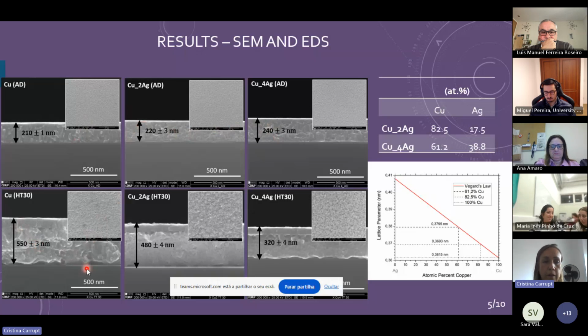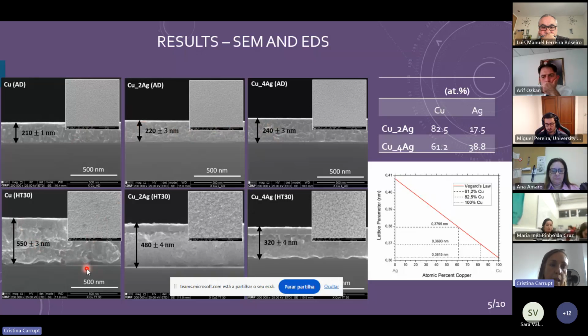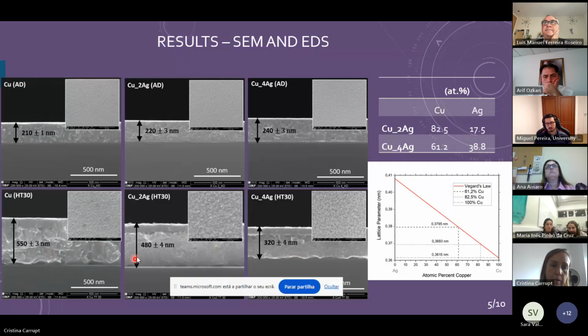With heat treatment, it promotes a severe increase in the thickness, and we see the film with more content of Ag, of silver. This growth is not so strong. This is because of the diffusion of Ag, of silver, to the grain boundaries, and it made the growth of thickness more difficult. Here, the content of silver was measured by EDS.